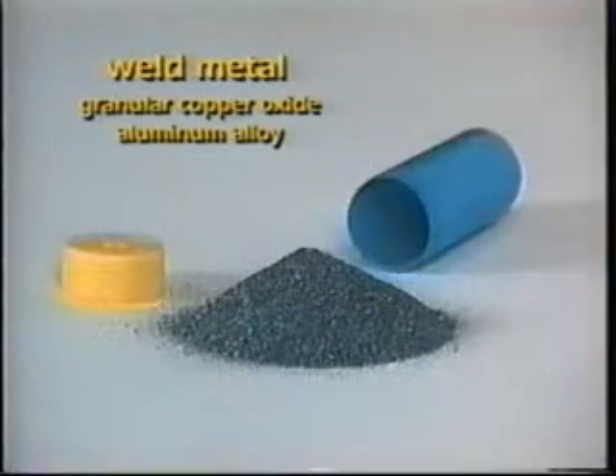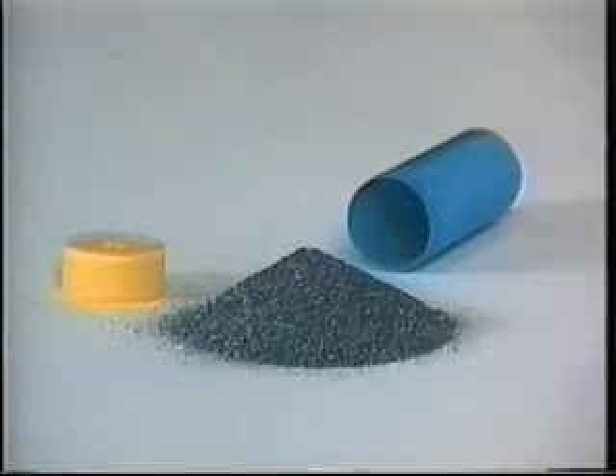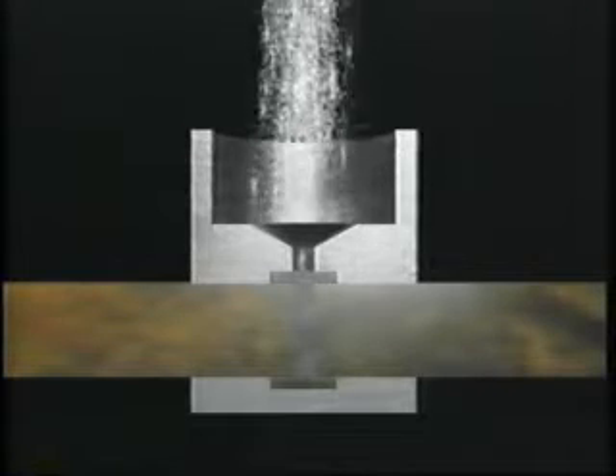The weld metal is principally composed of granular copper oxide and aluminum alloy. Through the exothermic process, a chemical reaction of the copper oxide by the aluminum produces molten copper alloy and aluminum oxide slag. The slag floats to the surface before the steel disc melts, allowing molten copper alloy to flow into the weld cavity and complete the weld.